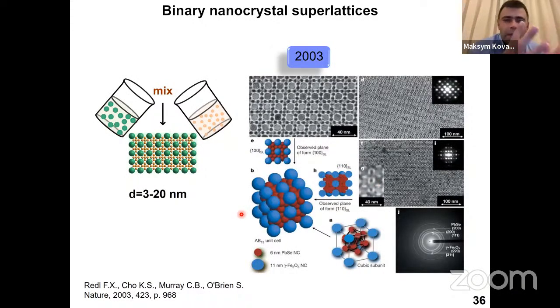And so then we thought, okay, as chemists, we can build more complex superstructures, not only simple cubic packing into supercubes, but we can combine perovskite quantum dots with some other materials or dielectric spacer quantum dots such that we can mutually orient the perovskite light emitters and see how that helps or not to build these coherent states, these collective states. Again, back in history, roughly 20 years ago, the first examples of binary nanocrystal self-assemblies had been reported by Chris Murray and his colleagues, who simply mixed two spheres of different sizes, sterically stabilized, as we discussed. And then upon solvent evaporation, they observed these crystal structures, which are identical to what you know in the atomic world, except that it's now built of nanocrystals as artificial atoms.